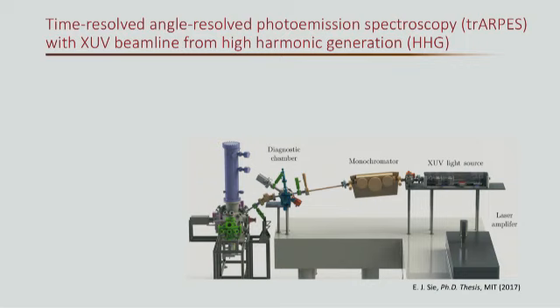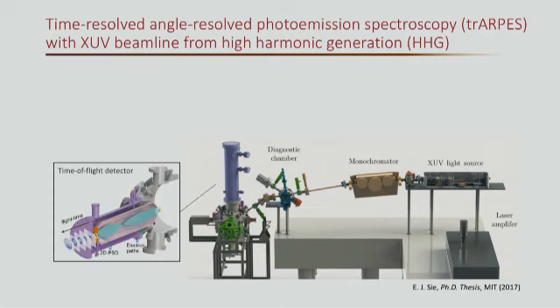The probe path is used to generate the XUV light source used to do the trARPES measurement. So we first generate the XUV light, where XUV stands for extreme UV light, and then use the monochromator to select the specific energy we want to use. And then it passes through the diagnostic chamber, and then finally is sent to the sample sitting in the center of this measuring chamber. Here you can see we have a pretty special type of detector, which is a time-of-flight detector.